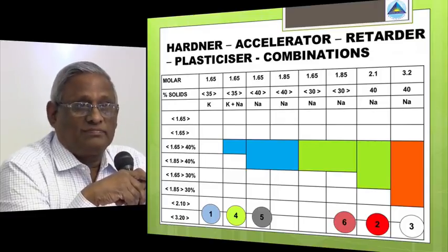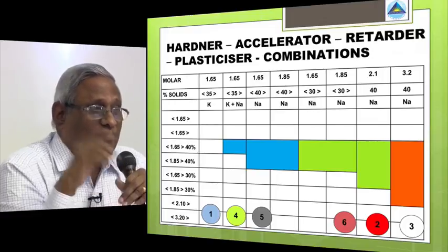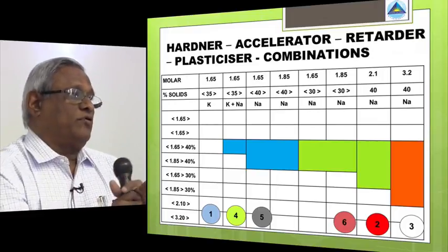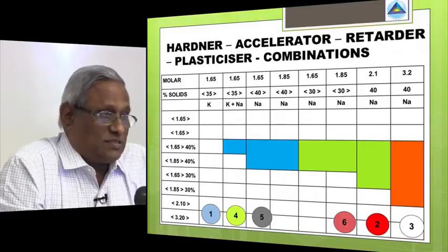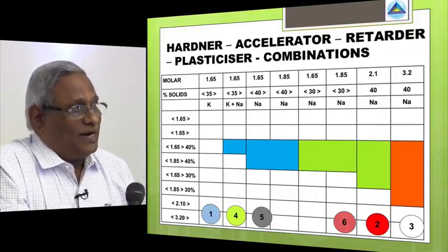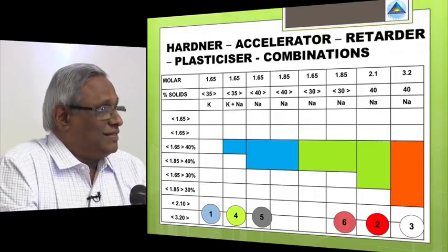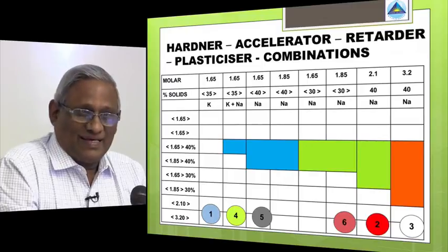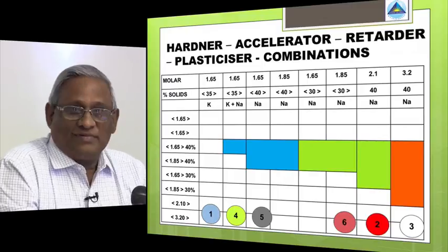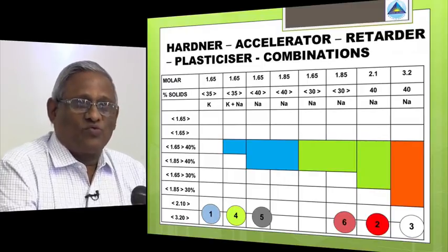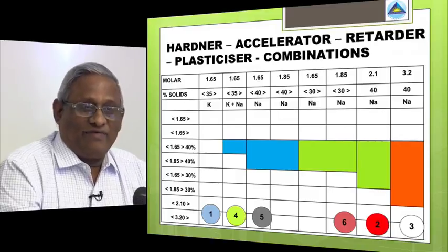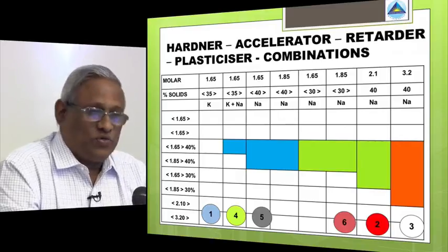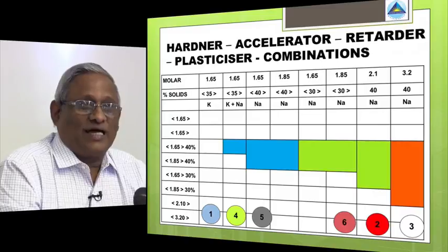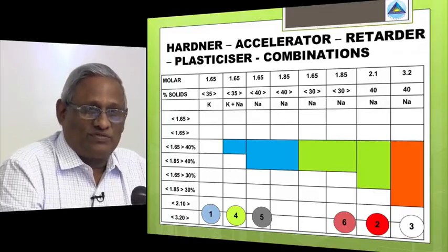They are 30% solutions. They work at an ambient of 25 to 30 degrees, and you don't have to add water at all. See, the reason why we have now prepared a product where we don't have to add water is normally in India, the concrete mixing is mason controlled. And the masons, we do not know how much water they mix, and even for curing, how much water they use, and what quality of water they are going to use.